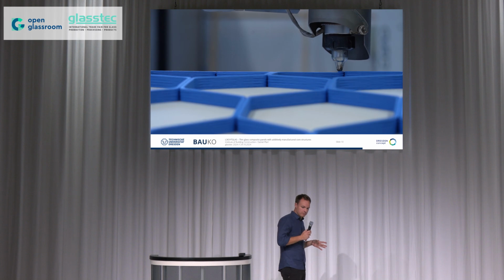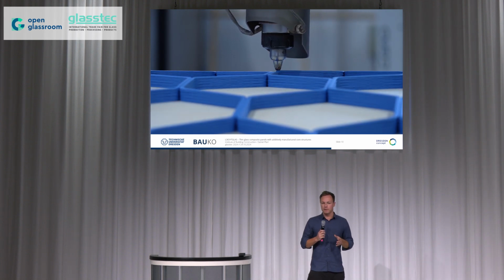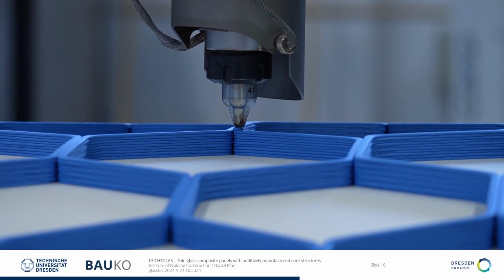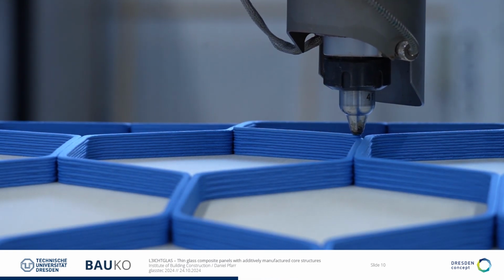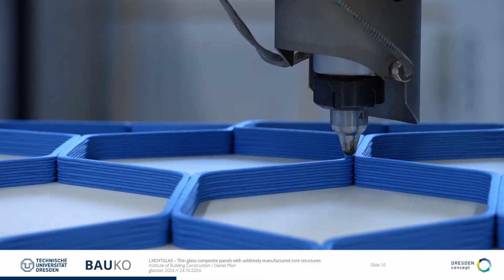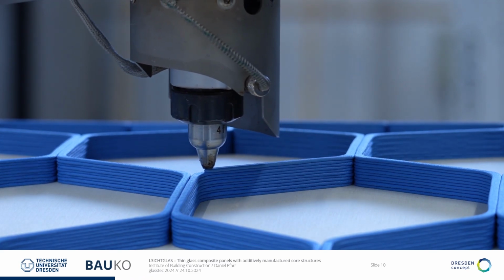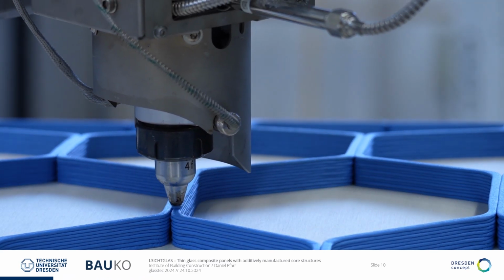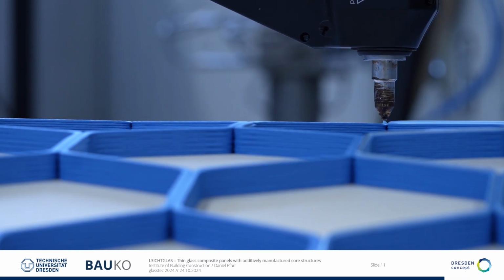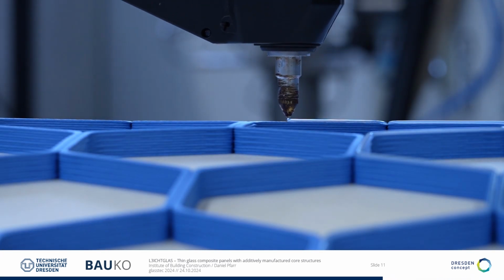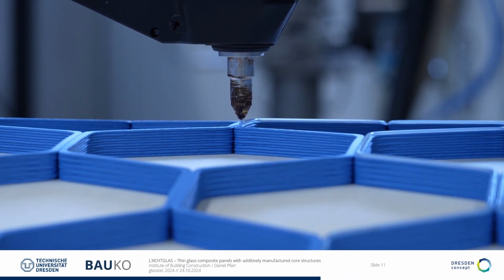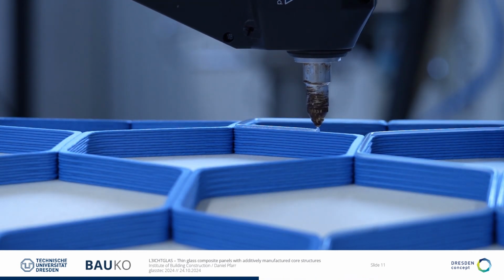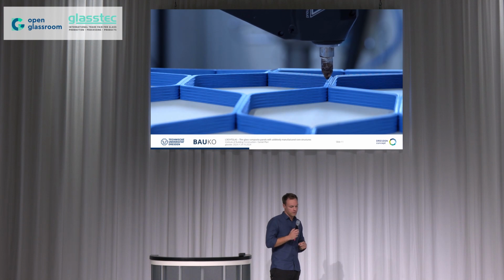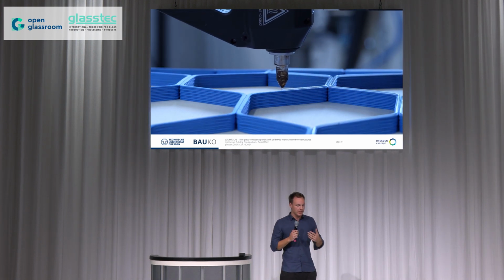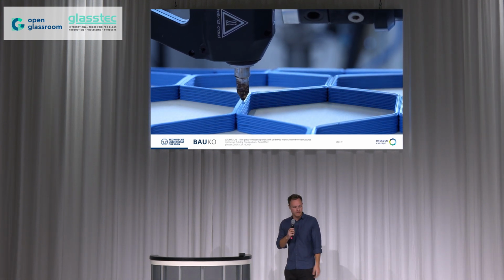When everything is prepared, then the production starts with the additive manufacturing. So this is the 3D printing process, and we are extruding here a polyamide with 35% glass fiber content in it. The extruder melts it up with 240 degrees and then deposits it according to the tool path. And in the same manner, we do it with the adhesive application. So that is a hot melt adhesive, which you apply on the same or on the top surface of the core structure. In this case, it is a polyethylene, which melts at around 110 degrees.